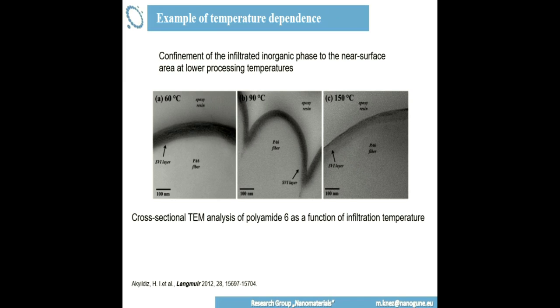Probably. There is a temperature dependence, of course, also for the diffusion. So this is cross-section areas. I did not copy it into here. It's PA6, but I think it was trimethyl aluminum, so aluminum oxide grown inside of polymer fibers, so polyamide fibers, so nylon 6 in this case, in dependence of the temperature. So you see that there are different shapes of the infiltrate and different gradients. The different depths which you can have here. And those, of course, will also change the properties of the